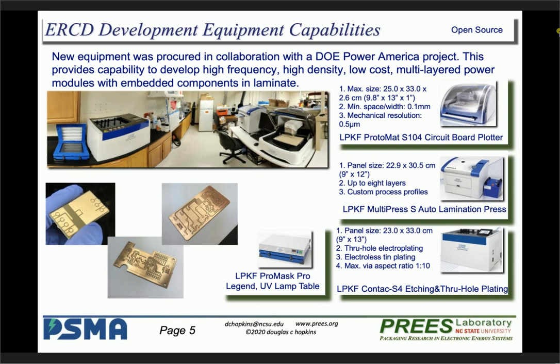So this is the equipment we use. We see up at the top, it's a mechanical router. You notice it has fairly good resolutions. These are phenomenal. We're talking about new wide bandgap devices that are getting smaller and smaller, or they're available at much higher power densities at much smaller sizes. Dr. Huang showed this could be a 16x reduction for the same power loss on die. So now you have smaller points of heat generation. However, if you get the larger die, you get much higher levels of current capacity, or we can also look at higher voltages.